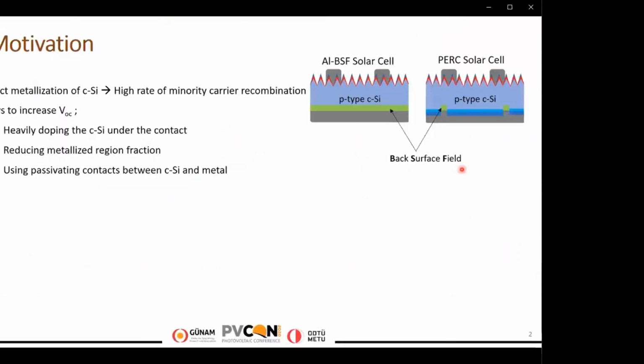Unfortunately, direct metallization of crystalline silicon leads to a highly recombinative interface, which limits the open circuit voltage of the devices. Here, common crystalline silicon solar cell structures, the aluminum back surface field solar cell and the passivated emitter rear contact (PERC) solar cell, are shown. PERC is an upgraded technology over the existing aluminum back surface field solar cell.